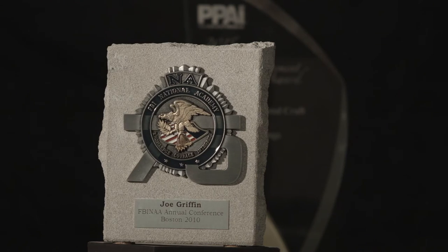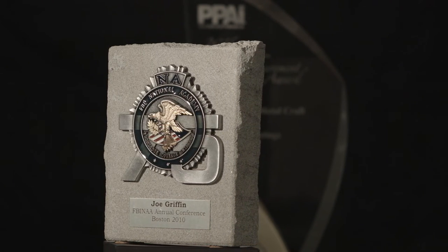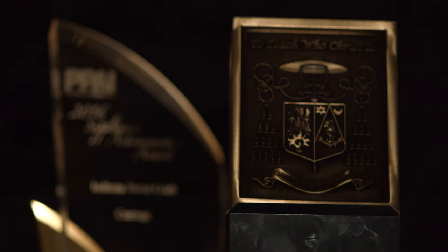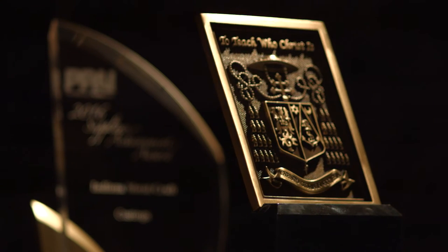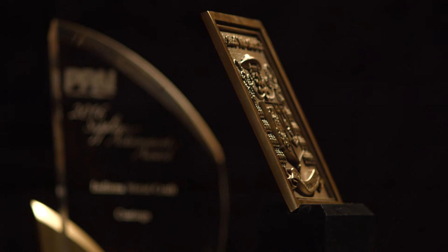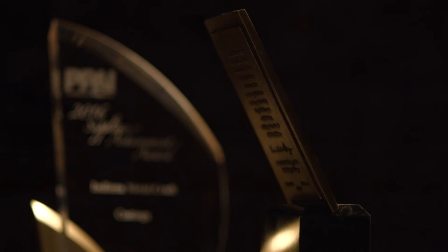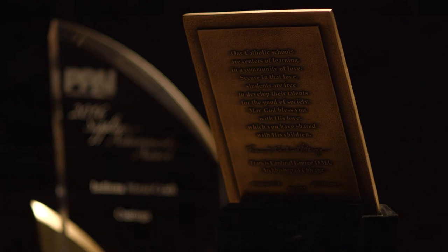The FBI Academy Award was enhanced with translucent hard enamel. The 4x6 Cardinal George Medallion is a great example of our lost wax casting capability. The solid brass casting was achieved by injecting waxes under high pressure into metal molds. Subsequently, the castings were made at 1,950 degrees Fahrenheit. Afterwards, the medallion was finished in our traditional satin brass finish.